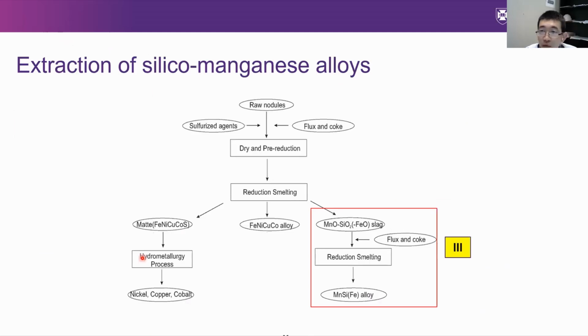So with the resultant manganese-rich alloy, we then extract the silico-manganese alloy from this slag to make the manganese silicon alloy. This can be widely accepted as the master alloys for steel making use.